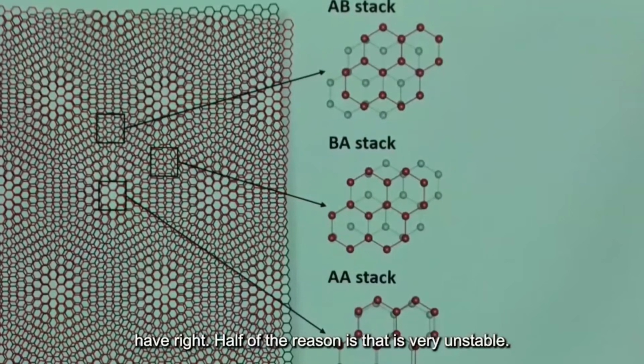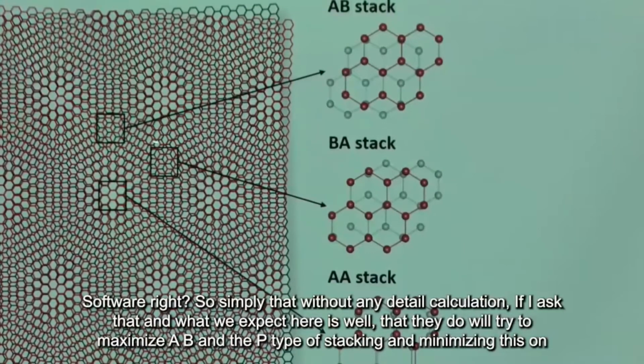We know that in nature there is no AA stacked graphite. Part of the reason is that it is a very unstable structure. Nature prefers so-called Bernal stacking, AB versus BA type of Bernal stacking. So simply, without any detailed calculation, if the lattice is deformable, we expect that nature will try to maximize AB and BA stacking and minimize the unstable AA stacking.